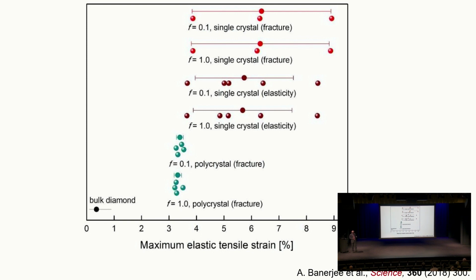And the reason behind this is you have very few defects. It's very clean, even though it's a CVD-made diamond. So we have, in the published paper in Science, a lot of transmission electron microscopy images of the specimen itself, and also atomic resolution micrographs. If you compare that to the polycrystal, it has many grains, it has many defects, so that you would expect it to have a lower ductility or strain to failure, and it fails around 3 to 4%. On the left, you see the bulk diamond.